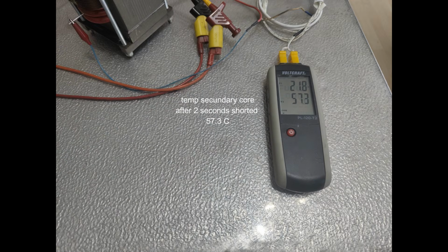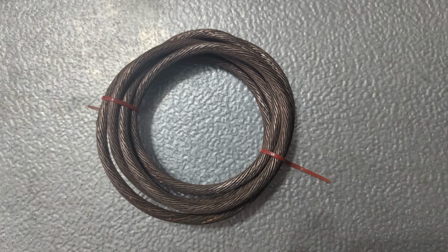And since very high currents can occur during spot welding, at least for the plans I have in mind, I need to watch the temperature of the secondary winding. Theory predicts that the temperature rises by roughly 20 degrees per second of welding, which matches this practical test quite nicely. And that most likely means I'll have to strip off that plastic insulation and switch to a heat-resistant covering. Oh well, so be it.